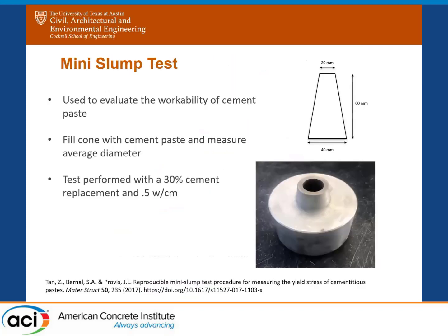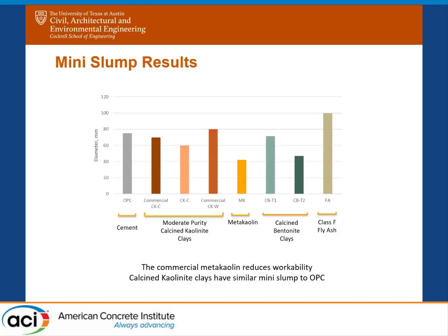So to determine workability, I use the mini slump test, which is just a smaller version of the general slump test at 60 millimeters instead of the full height. And here you can use paste instead of concrete, and also not the mortar flow because I didn't have quite enough material. So paste was used with the mini slump test. This test was performed at a 30% cement replacement and a 0.5 water to cement ratio. And this was really just to determine the difference between the metakaolin, which is well known in the field, versus these moderate calcined clays. So the results are here.